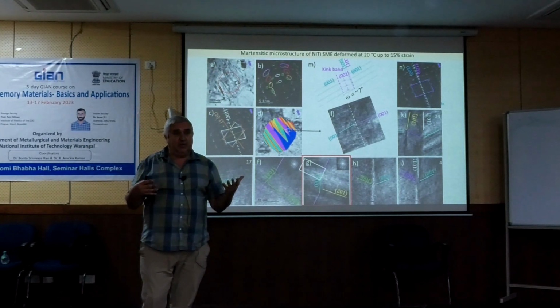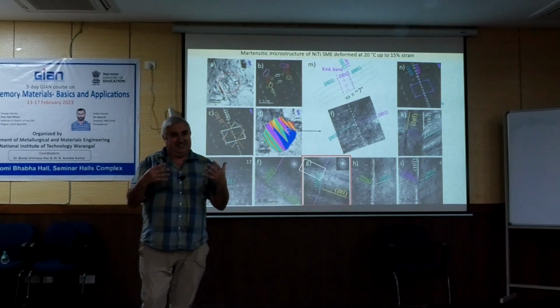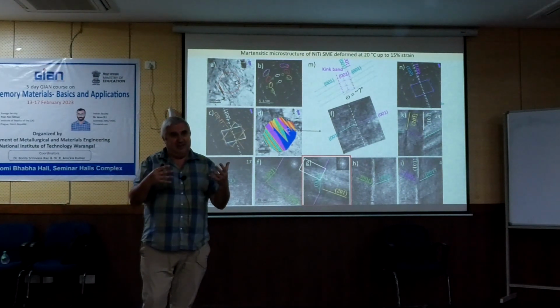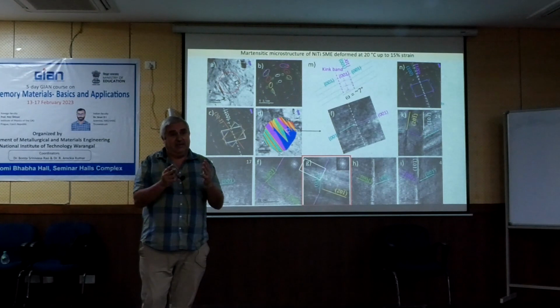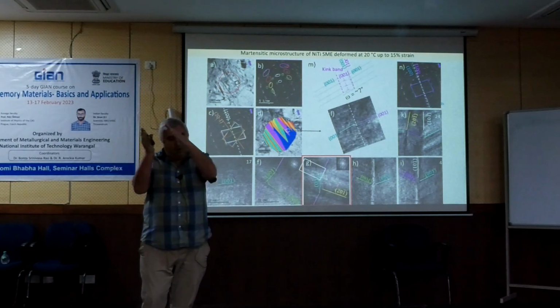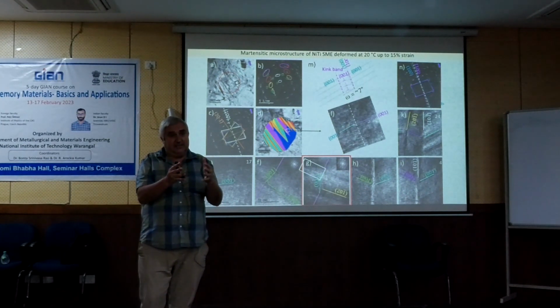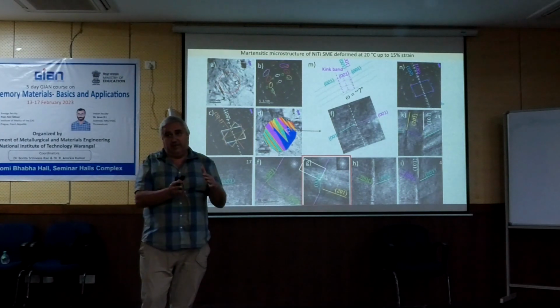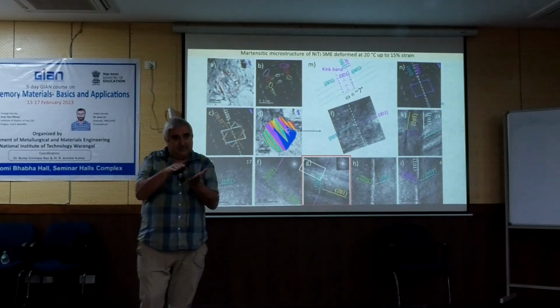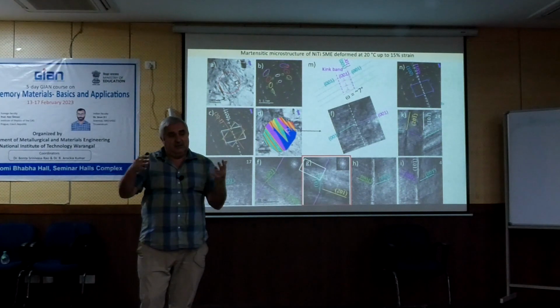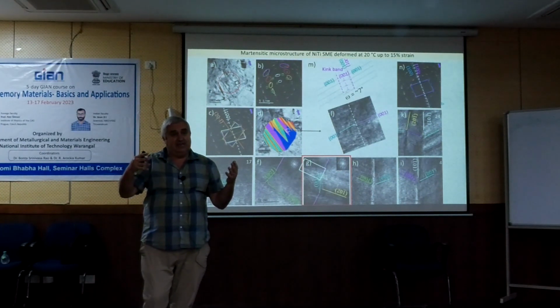And in geological materials, we know from the literature that the way the material deforms plastically is via kink bands. Kink bands are so-called bands of coordinated dislocation slip. They look like twins, but inside the lattice is slipped in a coordinated manner. This occurs because of the extreme anisotropy.